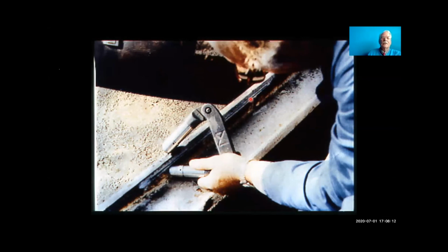So here we're doing a magnetic particle test. We've cleaned this and then sprayed on a magnetic ink, which has little tiny metal particles in it. And those get down into the crack. So you then clean off the surface, put on a developer, a white powder, bring along a magnet, and if there's a crack, you can see very clearly where the ink is coming out. It's a very good process.